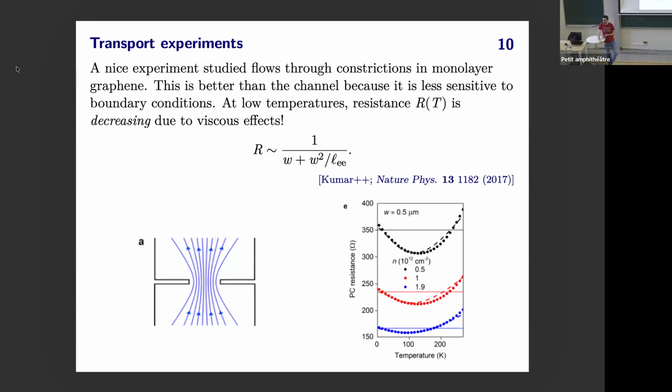It's not better just to focus on really low temperature, because at 100 Kelvin you have all the phonons, so mainly you're scattering by the phonons. In graphene, I think the electron-phonon scattering is pretty weak, so 100 Kelvin is still okay. Most of the scattering is going to be electron-electron. But indeed, there's a sweet spot: at too low temperatures you maybe just have ballistic transport. So you need to heat the system up enough so that L_ee is small compared to your device size, but not heat up too much because then the phonons kick in.